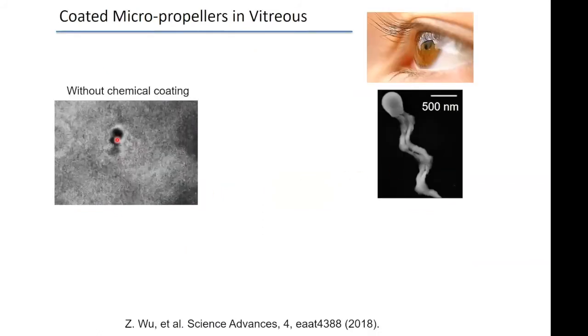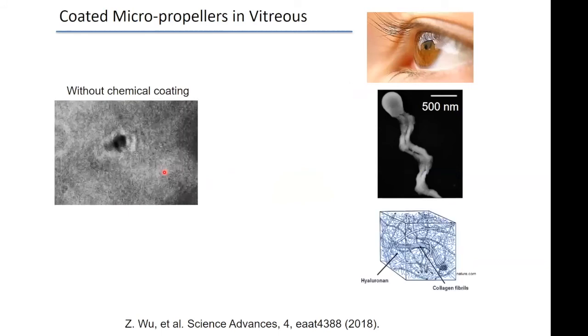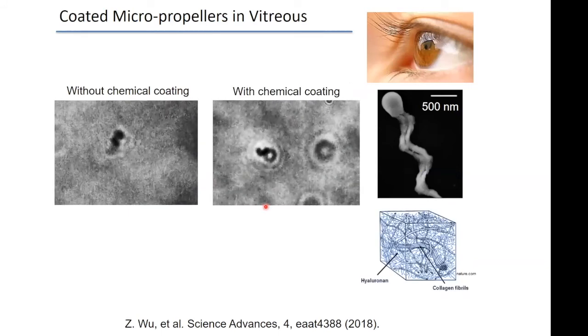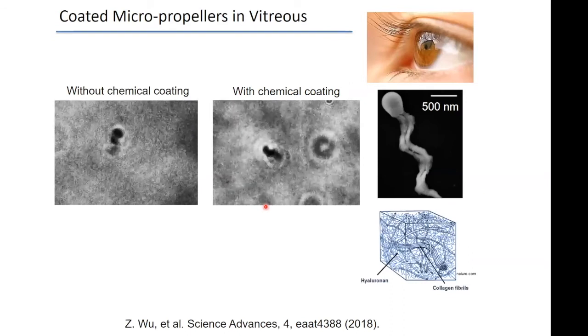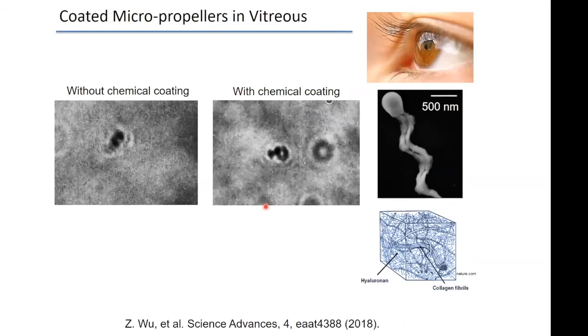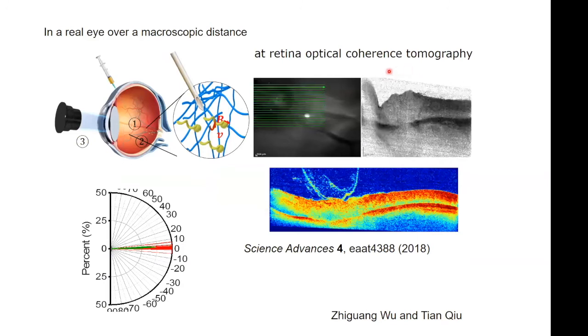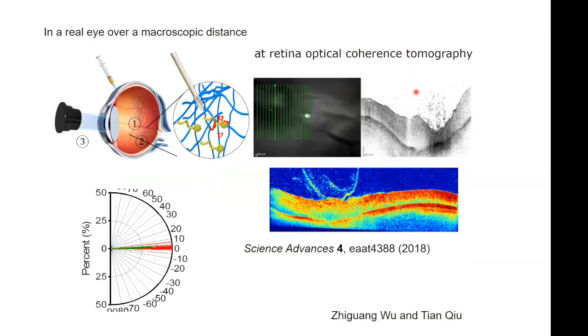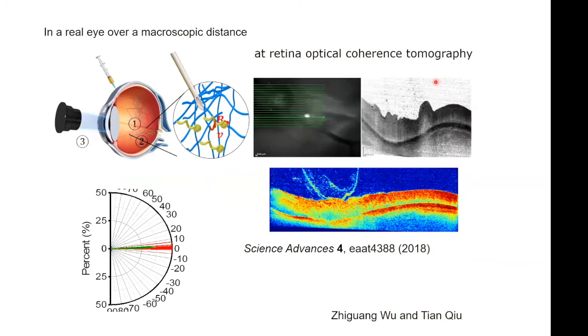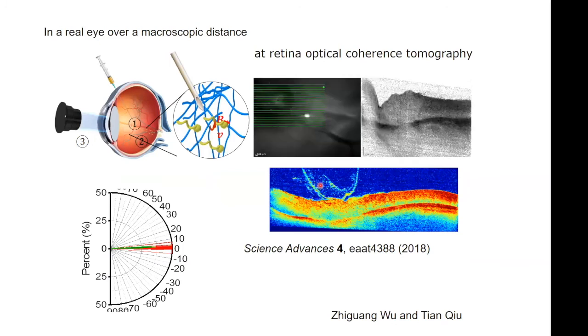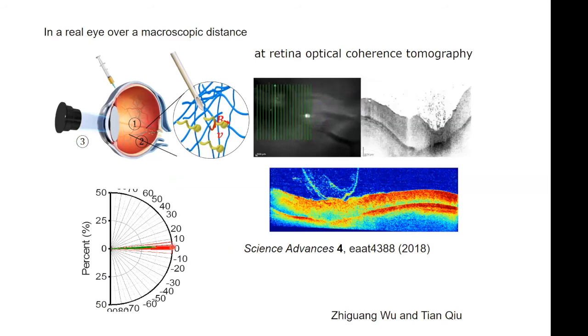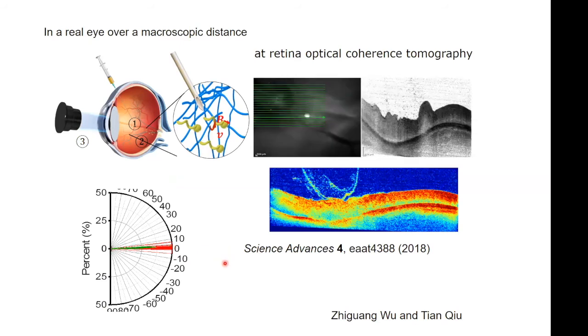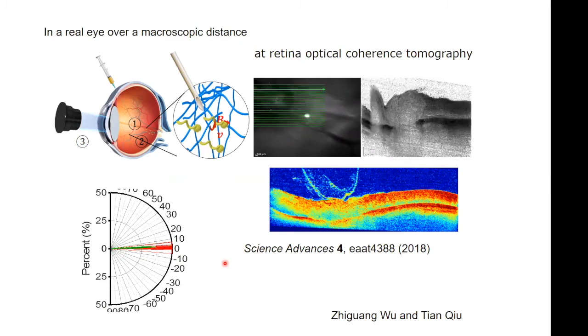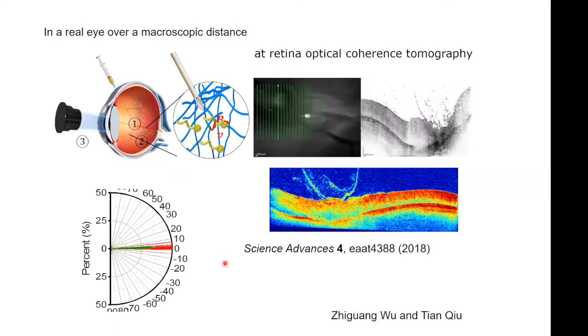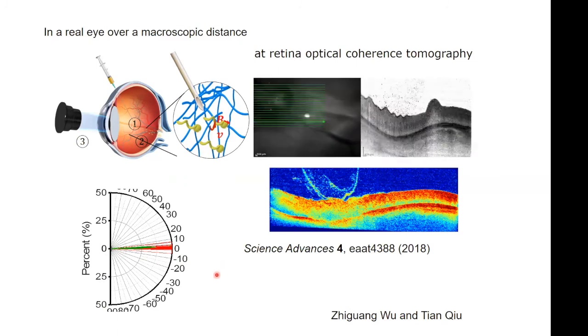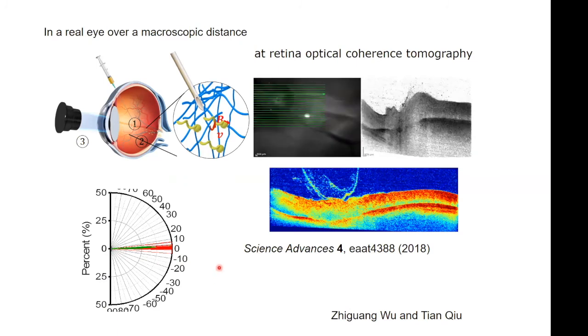And remember, the one without the coating got stuck. And if we have the coating, it is now able to travel through the vitreous. And so here is an OCT image where we see tens of thousands of them that have traveled about 1 centimeter with the coating through the vitreous and reached the retina. This is the image on the retina. And we see that they're very directional in their motion and they don't get stuck. And so this is a nice delivery agent. And we have, again, needed to overcome this problem of adhesion and the material. The size means we can use weak fields.